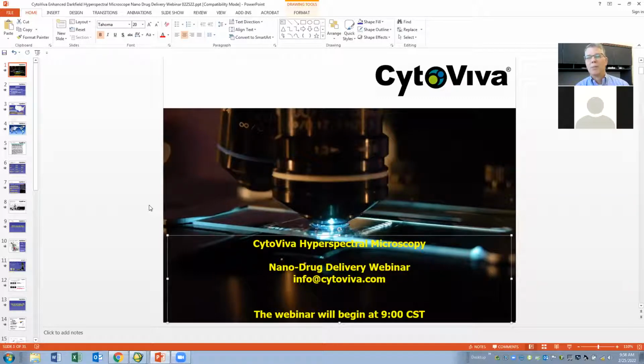I will say on plasmonic nanoparticles, though, as they get bigger, their optical spectrum redshifts in a fairly quantitative manner. So, for example, if I have 50 nanometer gold particles and I want to know if I have one or an aggregate, we know that a 50 nanometer gold particle in a refractive index media of water is going to have a reflectance optical spectrum of about 560 nanometers. And if there's an aggregate, that's going to redshift.